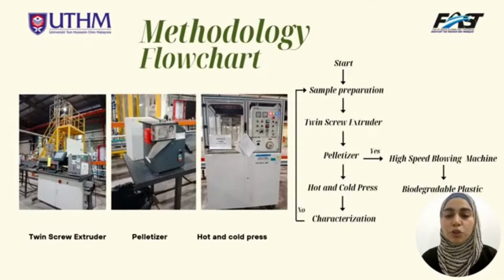If we talk about the methodology, first of all, we need to prepare the sample. We cannot directly mix the black soldier fly exuviae into the LDPE. First, we need to prepare the black soldier fly powder. Then we need to mix it with the LDPE. But still, we cannot directly mix the black soldier fly exuviae powder with LDPE. We need the plasticizer and compatibilizer in order to bring the compatibility between the black soldier fly exuviae and the